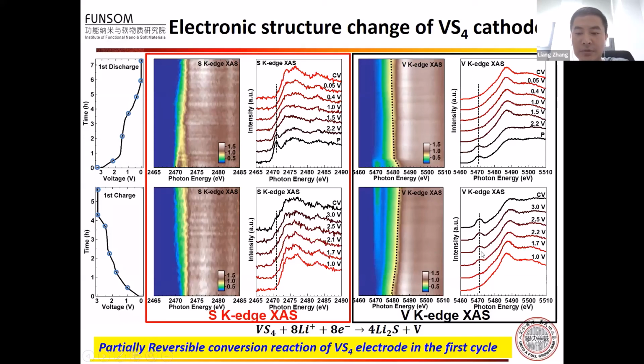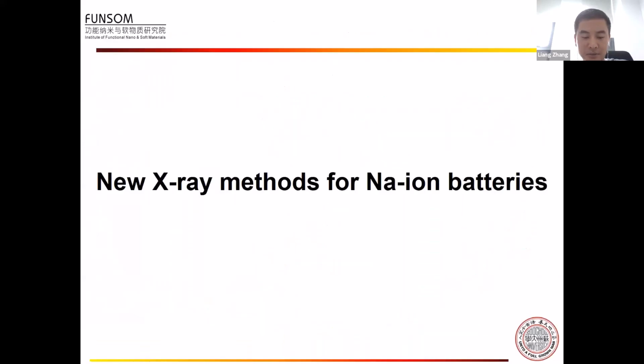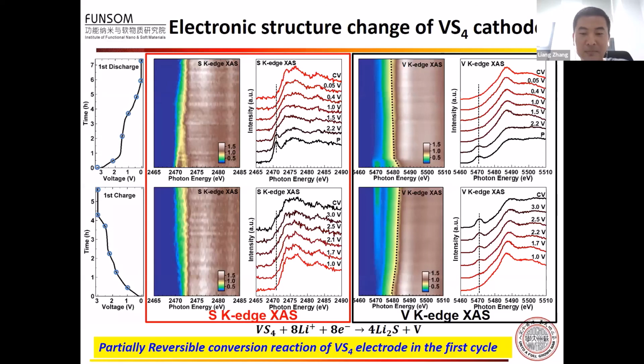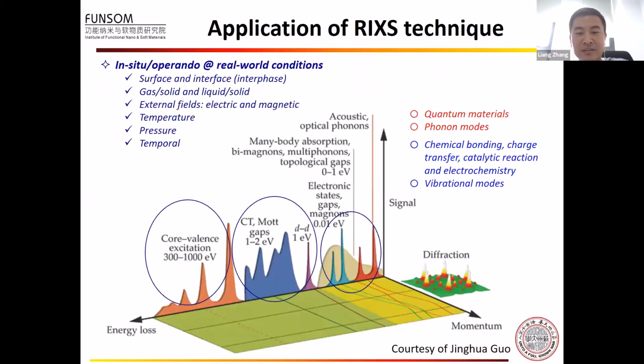During the following charge process, the pre-edge feature is reformed, and the main absorption edge gradually shifted to higher binding energy. So this result clearly indicates that the conversion reaction of vanadium sulfide is partially reversible, with lithium sulfide and metallic vanadium as the final reaction products. So this is the second part. Because of the time issue, I will skip the third part.